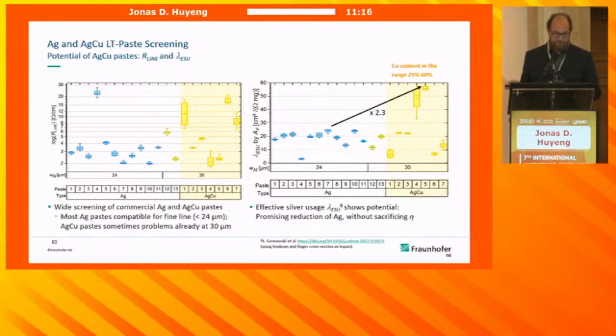On the left-hand side, you can see the line resistivity on fingers on a logarithmic scale, and then you can see the left part is silver materials, the right part is silver-coated copper. There's a little detail here that they have been printed with different finger openings, and you can see that for most silver paste, it's pretty good printable for openings from 24 micron width. The silver copper particles, there's some materials that are not yet there in terms of printability, so they have an increased line resistance,